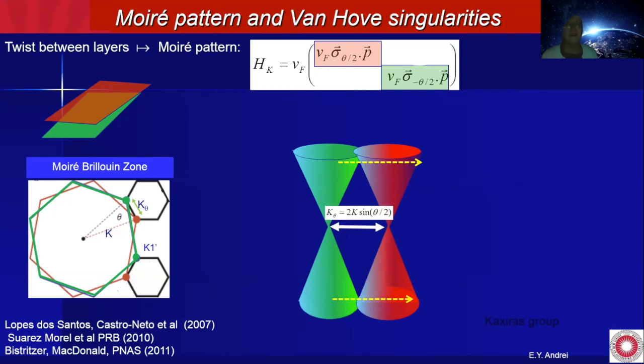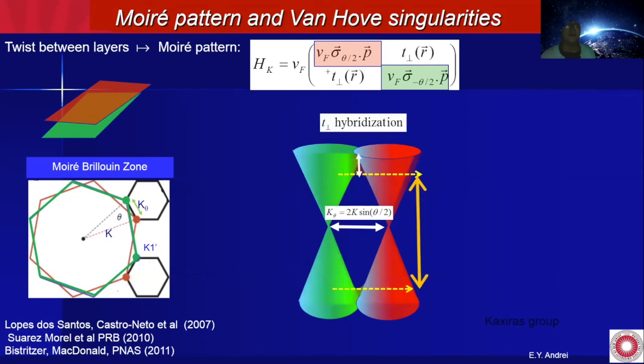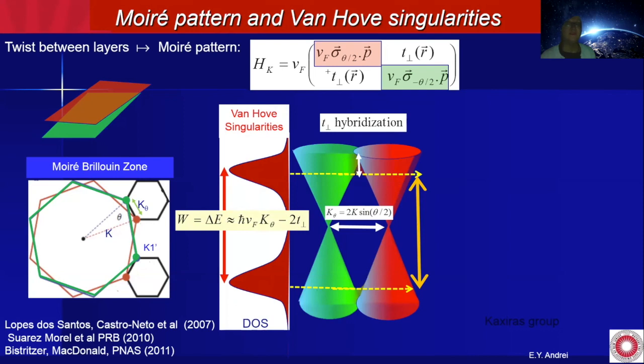Now, as long as there's no tunneling between the layers, the layers don't care about each other. However, as soon as tunneling occurs between the layers, you have a hybridization between them, and that gives rise to a saddle point in the band structure, which translates into a singularity, which we call a Van Hove singularity, in the density of states. These Van Hove singularities are marking the bandwidth. So we have a new mini band that has shrunk by an amount that corresponds to the twist angle, and its bandwidth is just the distance between the two Van Hove singularities.